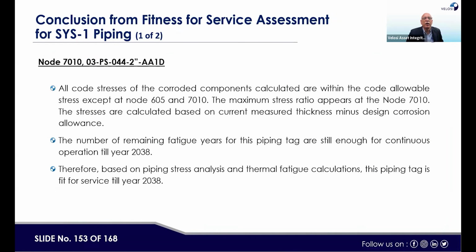If you see that, all code stresses of the corroded component are calculated within the code allowable stress except at node 605 and 7010. The maximum stress ratio appears at node 7010. These stresses are calculated based on the current measured thickness minus design corrosion allowance. The number of remaining fatigue years for the piping tag is still enough for continuous service till year 2038. Therefore, based on piping stress analysis and thermal fatigue calculation, this piping tag is fit for service till year 2038.